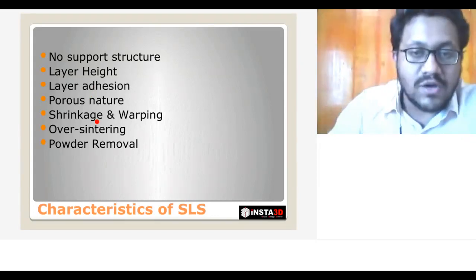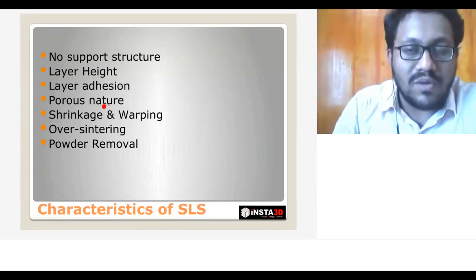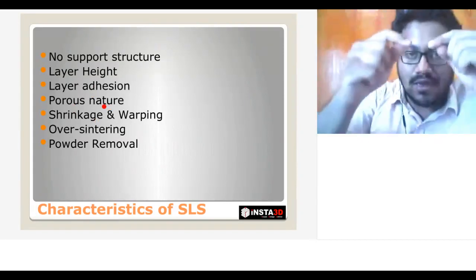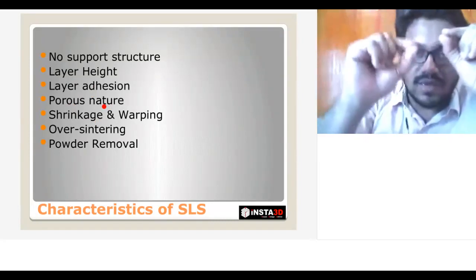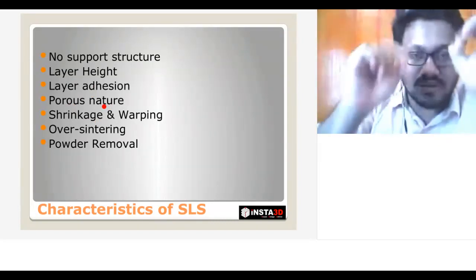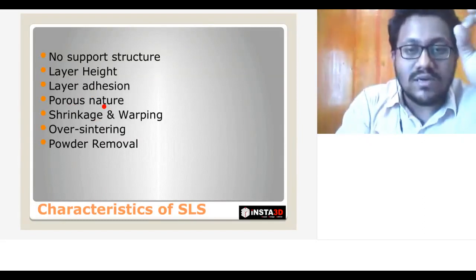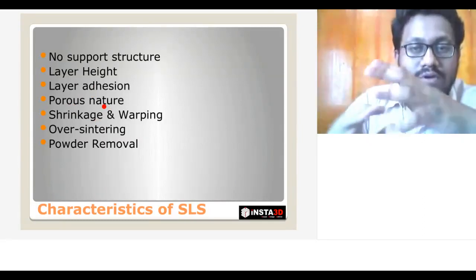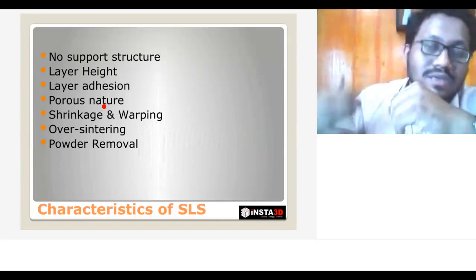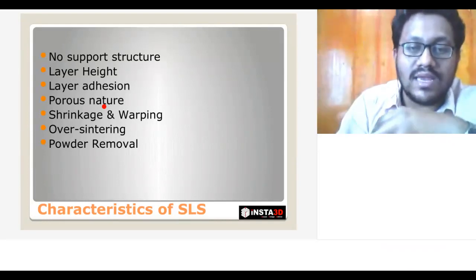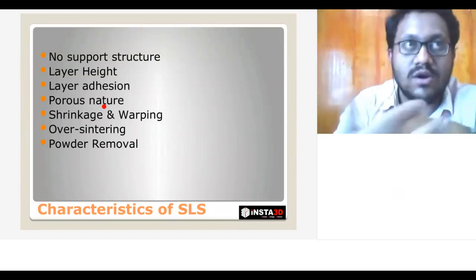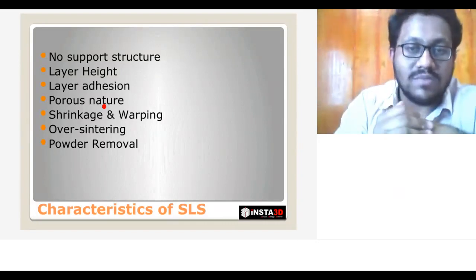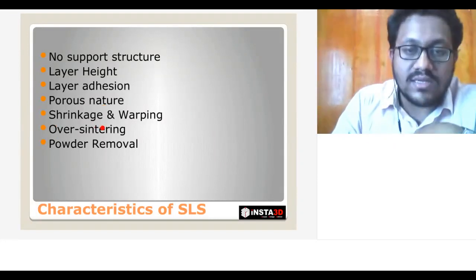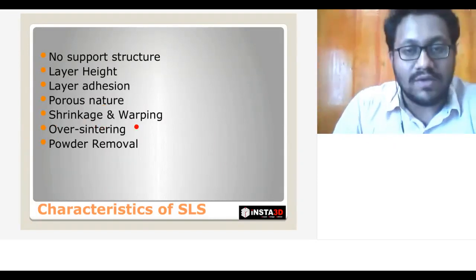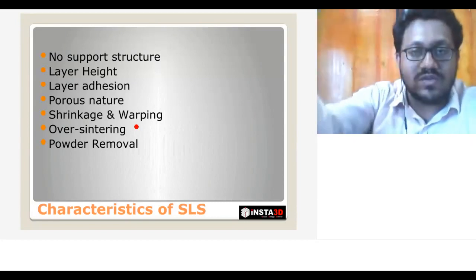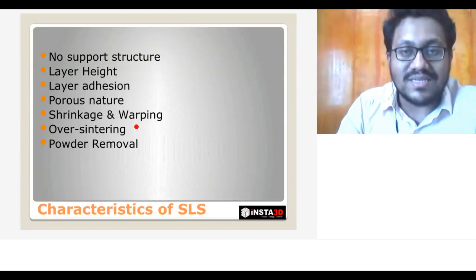It's because of the porous nature of the 3D printed component. Since we use powders, the powders when sticking, there will be a small gap in between the molecules of powders. So the porous nature makes it to look a bit rough or matte finished. So we can just dye it, or we can use any other post-processing technique in order to improve the quality of the 3D printed component. So here also there is a problem called a shrinkage and warping effect, and it's similar to the things which was discussed in FDM and SLA techniques.